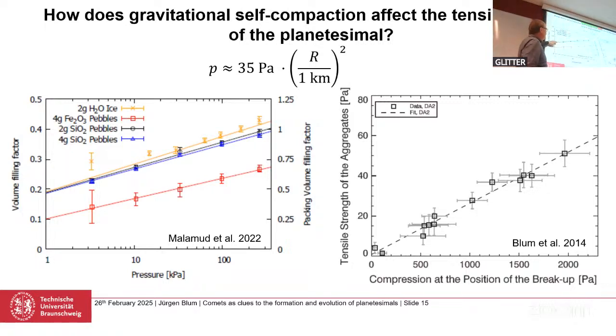So the compression is also little, but here the tensile strength is shown. And the tensile strength for uncompressed millimeter pebble piles held by van der Waals forces is on the order of 1 pascal. So this is not 0, this is 1. But as we go from a very tiny planetesimal to a 1 kilometer object, we're going through higher tensile strength.